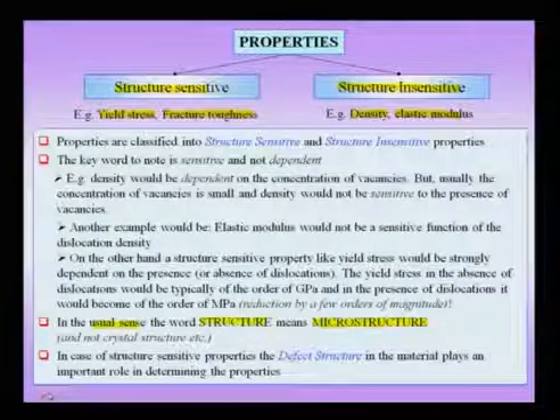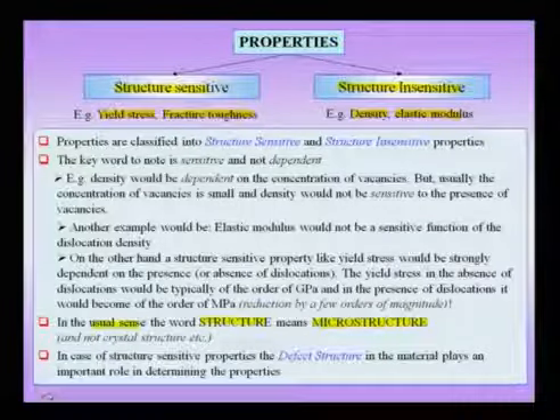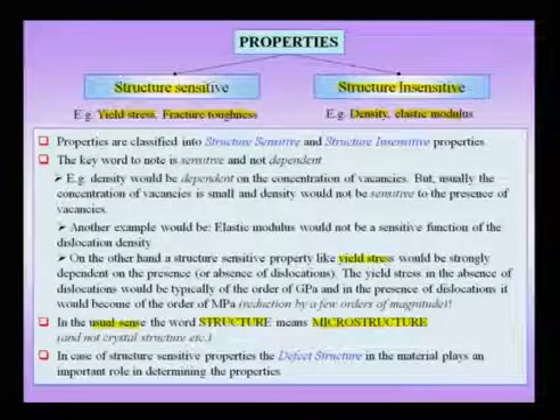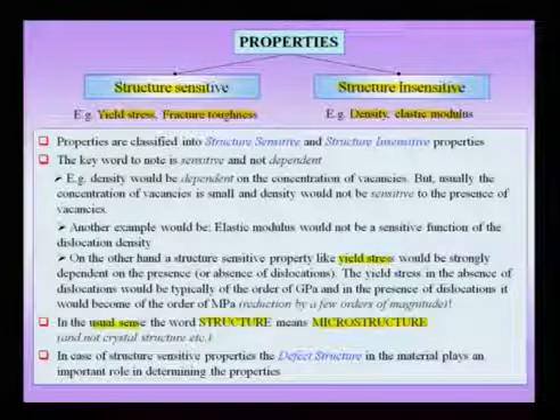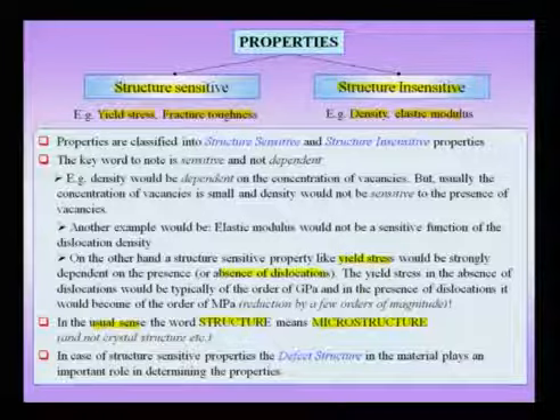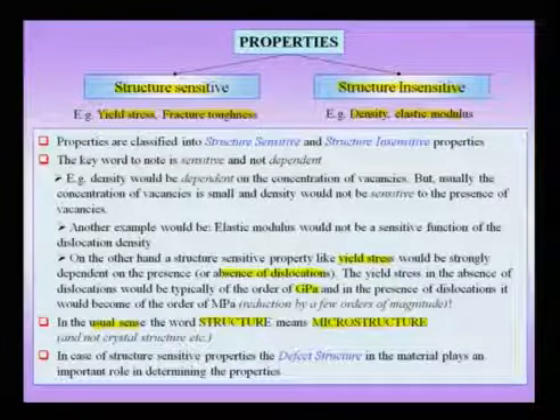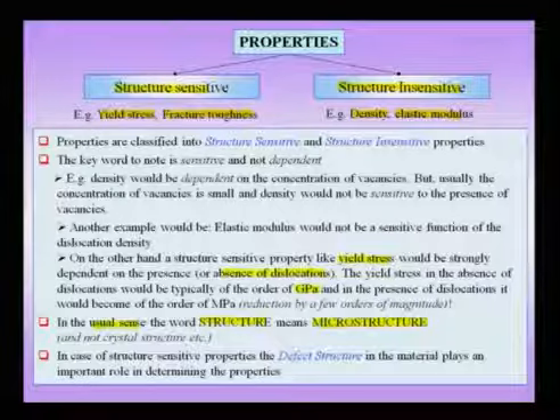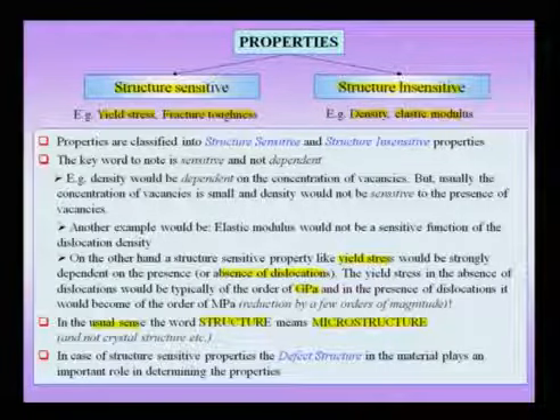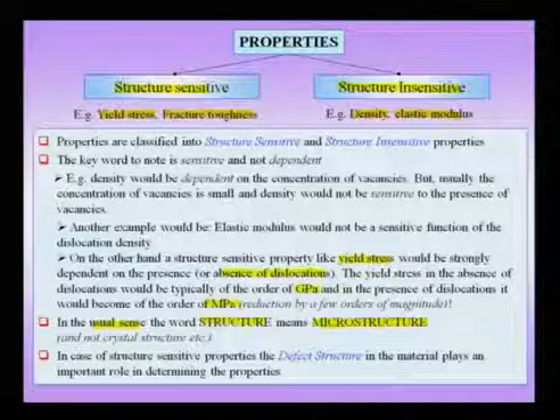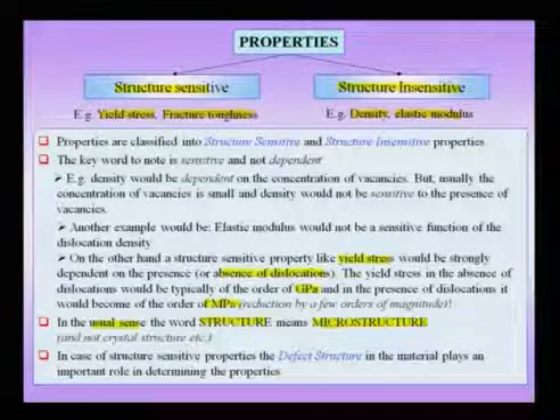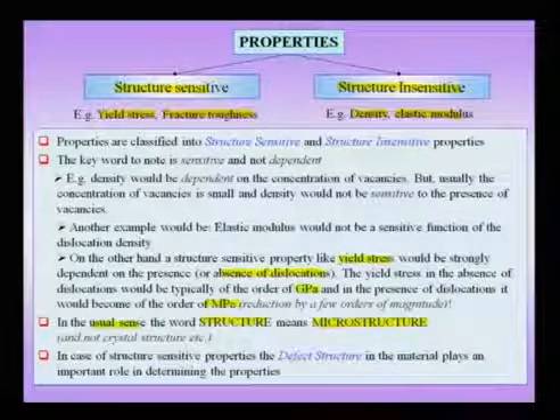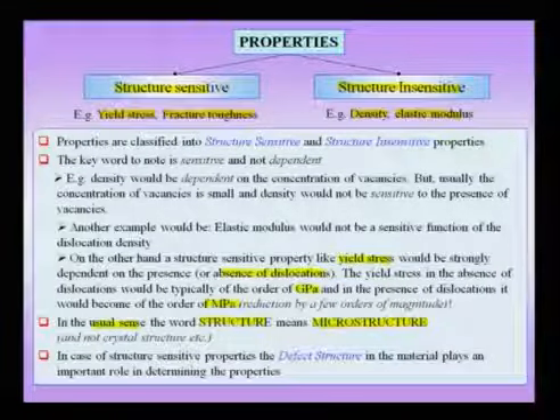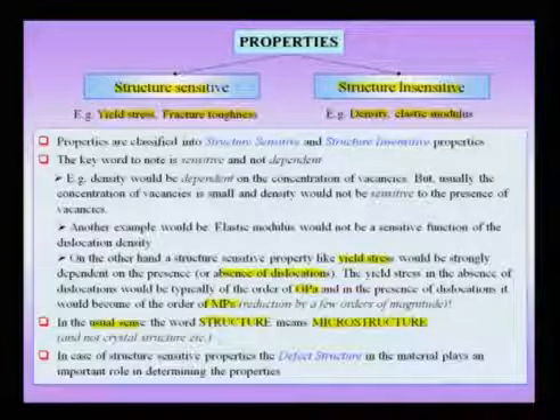So, let me summarize this slide by giving this example. Suppose I am talking about a microstructure sensitive property like yield stress, which in the absence of dislocations can take a very high value of the order of gigapascals, but in the presence of dislocations the crystal is severely weakened and the yield stress typically turns out to be of the order of megapascals. It could be hundreds of megapascals, but definitely a few orders of magnitude lower than if the crystal had no dislocations in it. Therefore, properties have to be understood in the context of structure sensitive and structure insensitive properties.